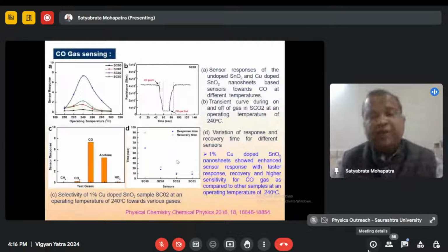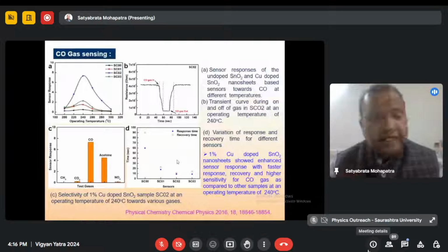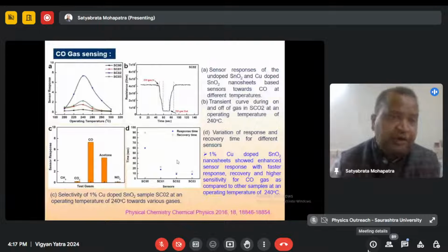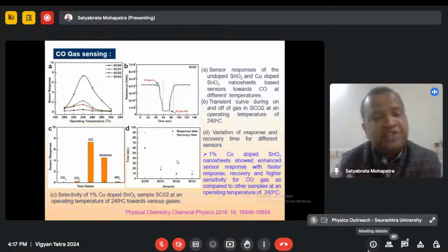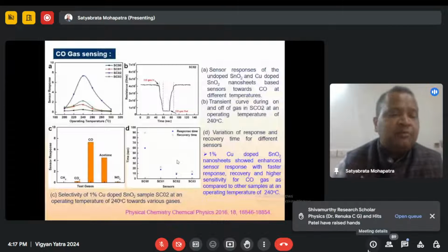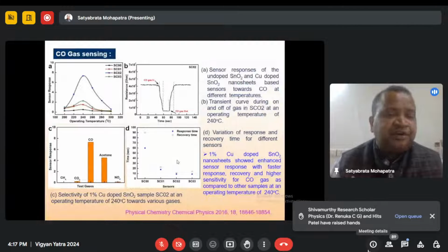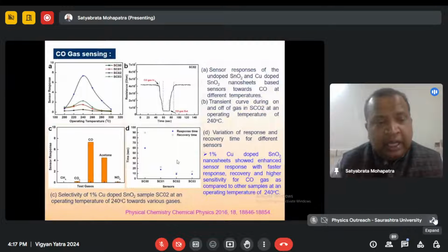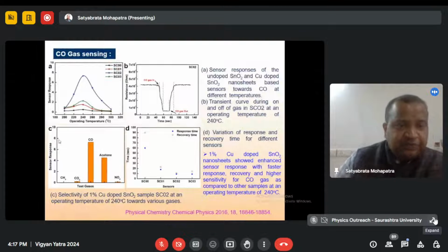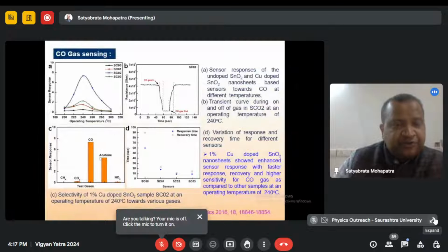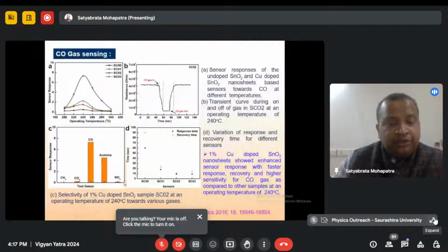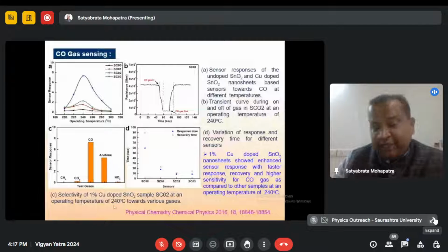Another criterion which is important for developing a gas sensor is selectivity. When you test it against other gases, because you will not have only carbon monoxide, you have an array of gases, it has to have selectivity for carbon monoxide. That's what is required. And you can see in C the sensor response: there is a selective sensor response for carbon monoxide, which is the highest. Of course, there is interference with acetone, but the other gases are negligible. So this shows a good selectivity.